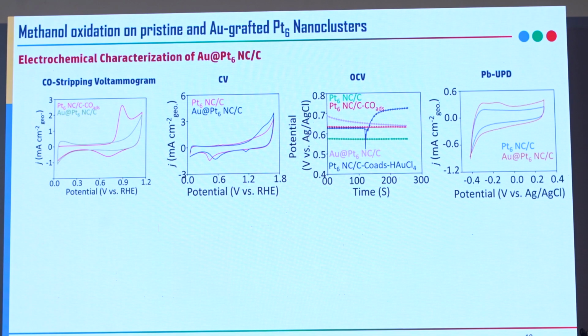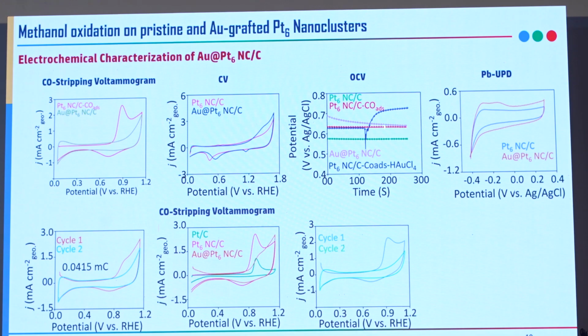And from the CV analysis, you can see there is a formation of a gold oxidation and gold oxide reduction. That is the confirmation for the gold decoration. And the OCV and Pb-UPD also applied for this gold decoration on the surface of these Pt6 nanoclusters.